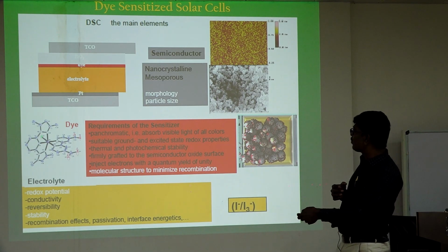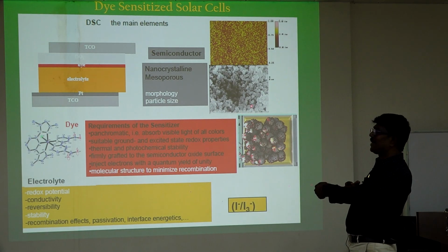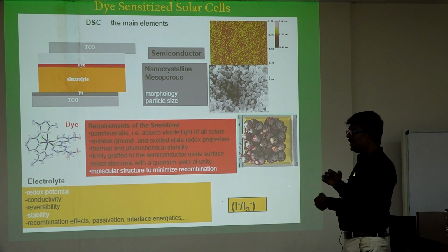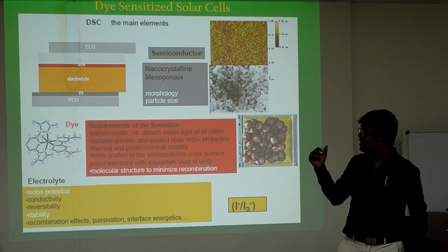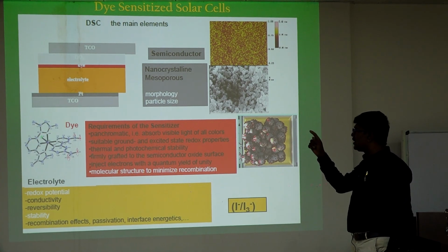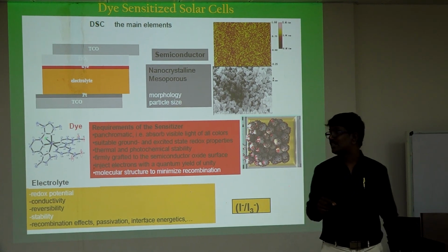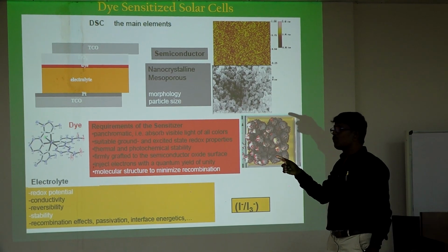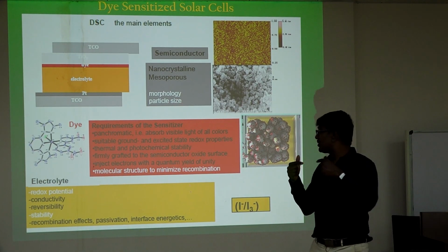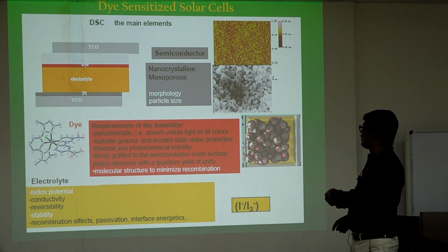And then when you put the dye molecule, the dye molecule can adsorb on the surface of the particle. You can see the dye molecule gets adsorbed on the surface of the particle like this. So it will be an adsorption phenomenon. How this is adsorbed, I can show the structure of the dye and explain. This dye molecule has a carboxy group, the anchoring group. The COOH group will anchor on the titanium oxide by hydrogen bonding on the molecular surface. So you can adsorb the compound on the surface like this. Okay, this is a point.